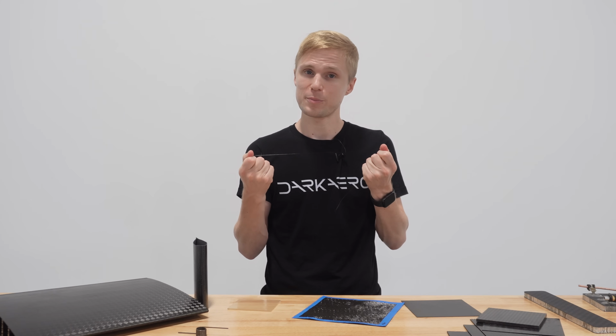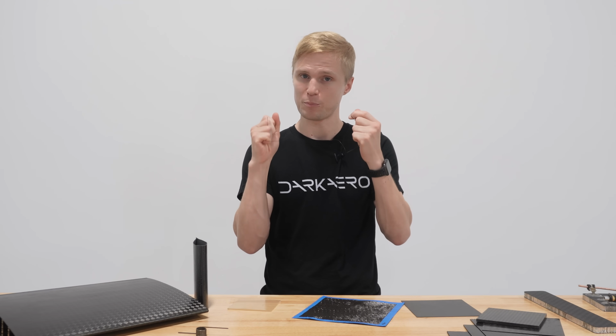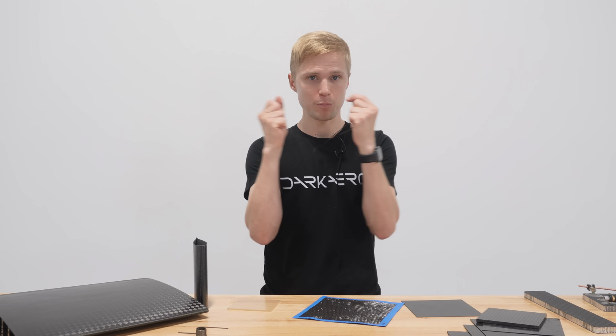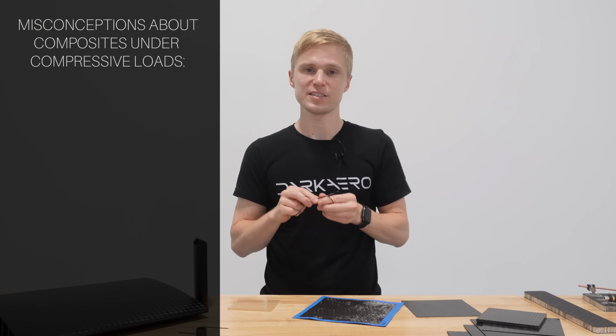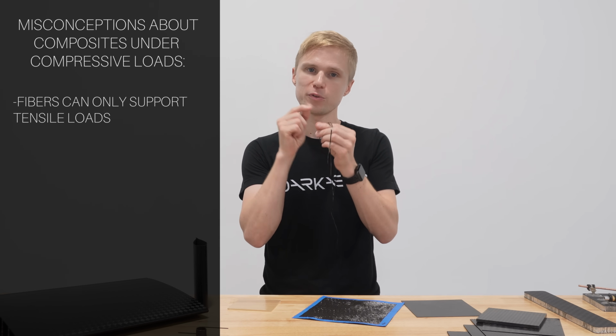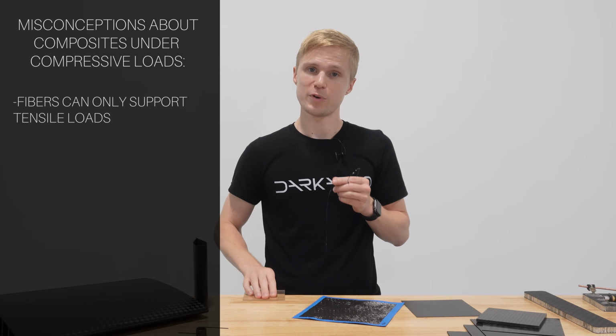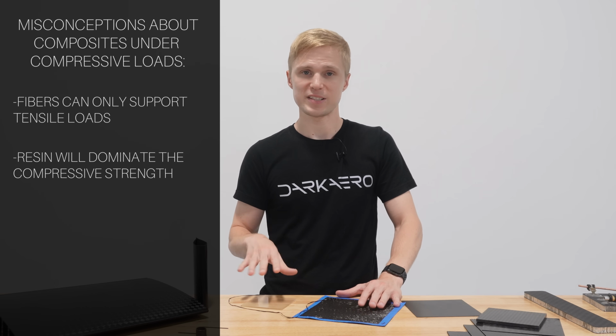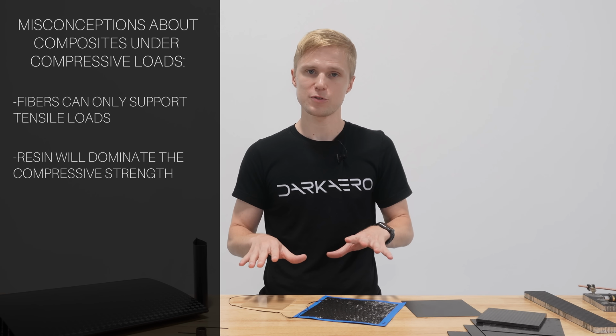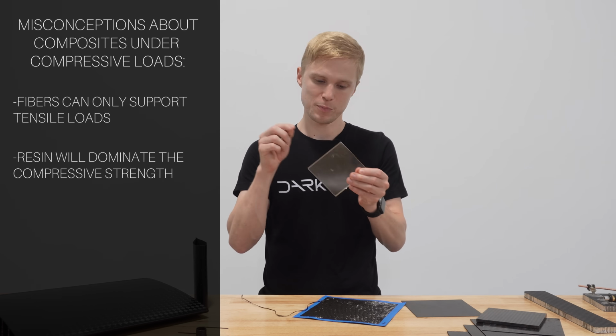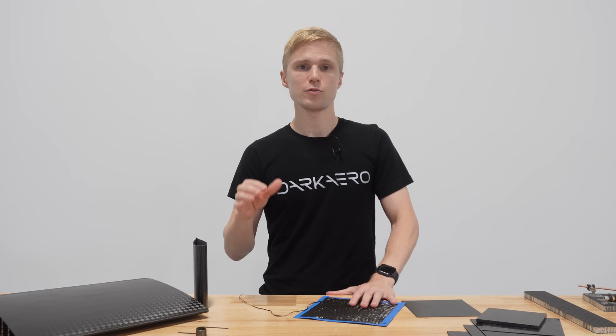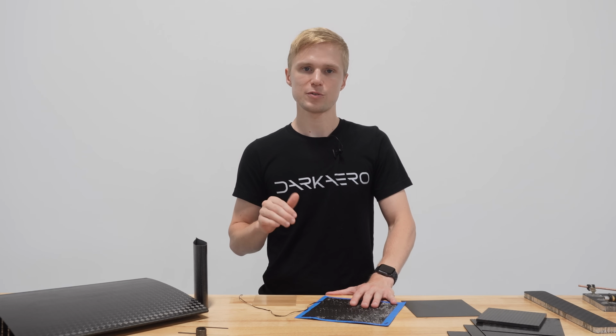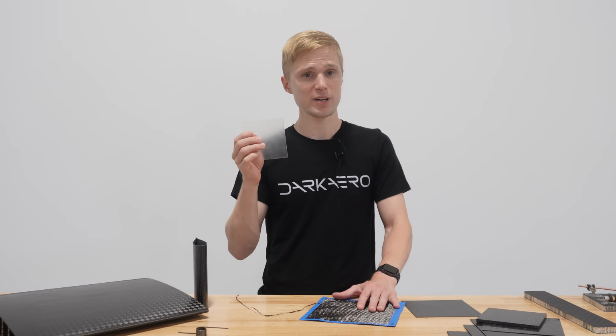Like a rope, carbon fibers in their raw form are strong and stiff when pulled in tension, but they'll collapse when pushed in compression. This analogy leads to the incorrect conclusion that the fibers only support tensile loads, even when combined with a resin matrix material. An alternative but still incorrect conclusion is that the compressive strength of the composite will only be the compressive strength of the resin. The truth is found when looking at actual measured strength values for carbon fiber composites, both in tension and compression. While the compressive strength is less than the tensile strength, it is far from zero, and commonly much higher than the compressive strength of just the resin alone.